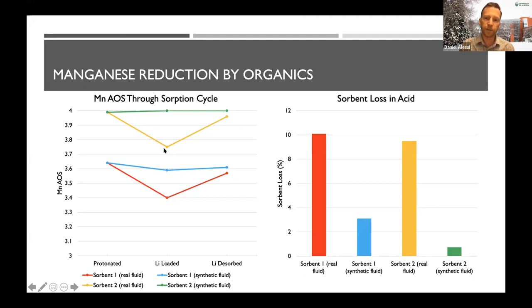And so what that's telling you naturally is that some of the manganese 4 must be converted into manganese 3, or it ends up manganese 2 as well. And that is a reduction. Manganese 4 is the oxidized version. It means that something in the chemistry of the brine is transmitting electrons to the manganese and reducing it. It's making it become manganese 3 or manganese 2. Then when we put it in the acid, we see it recovers back to manganese 4. Well, that makes sense, because manganese 3 and manganese 2 are way more soluble. They go back into solution way more easily than manganese 4.